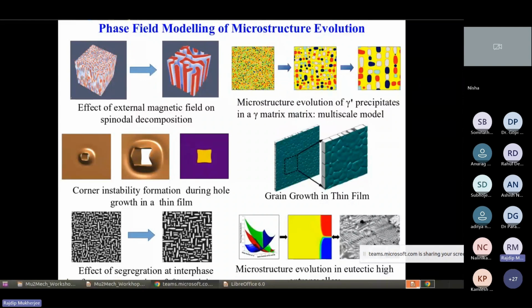The second one you can see is the microstructure evolution of gamma prime precipitate in a gamma matrix using a multi-scale model. It's very similar to what we are showing you in this Mu2Mech. And this kind of microstructure is particularly important for turbine blade or turbine disc applications. This is a precipitation hardened alloy, which is a nickel-based superalloy. And most of the metallurgical systems are not pure metals, but alloys, and most of them are precipitation hardened alloys, like these Inconel-based superalloys, where you can see this cuboidal precipitate aligned in a particular direction, responsible for the strengthening of this nickel-based superalloy, which is used for turbine blade application.